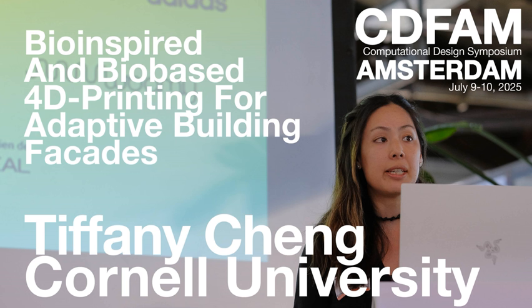And then with the assurance from our extensive testing, we then rented a total of 4 3D printers to fabricate almost 450 bespoke shading elements. So each of them were unique. And because of this very material efficient structure, each of these only took, on average, 20 minutes to produce. And the whole process of 4D printing the facade took 17 days and less than 6 kilograms of material.